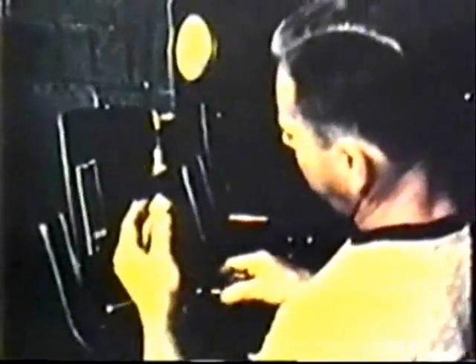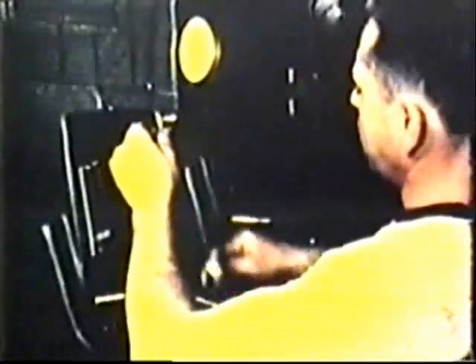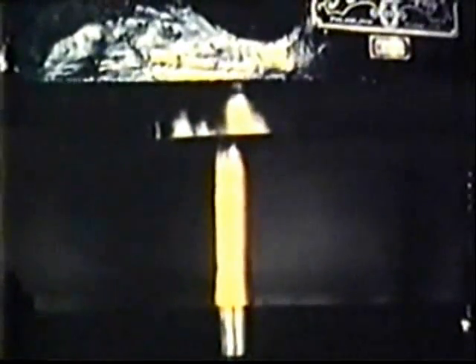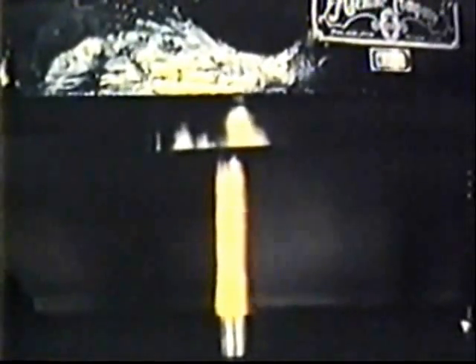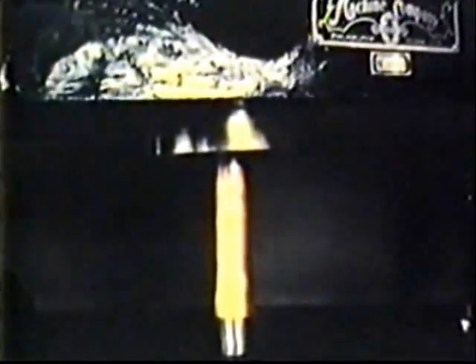Because customers request a specific hardness in their finished tubing, an additional test must be performed. A prepared sample is subjected to a Rockwell hardness test, which indicates both normal and superficial hardness values. Tests also are conducted to determine the tensile strength, yield point, and elongation properties of the tubing. Samples are given an expansion test by forcing the tube over a tapered mandrel. These and many other tests determine the fact that the complete requirements of the customer have been met.